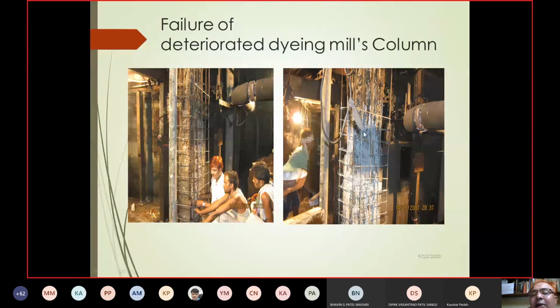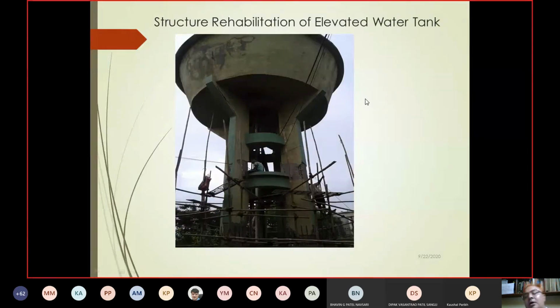We can say styrene rubber, because this is old concrete and a new material should be there. We are using micro concrete. It gives 25 Newton per mm square strength within 24 hours. Micro concrete should be used, because you cannot wait for 28 days to gain strength.